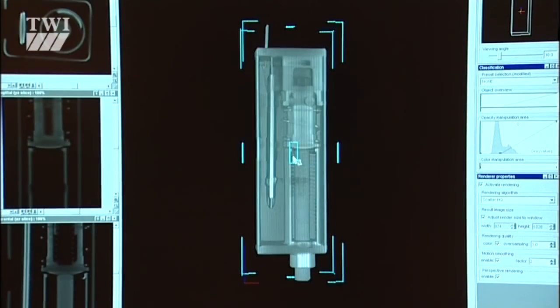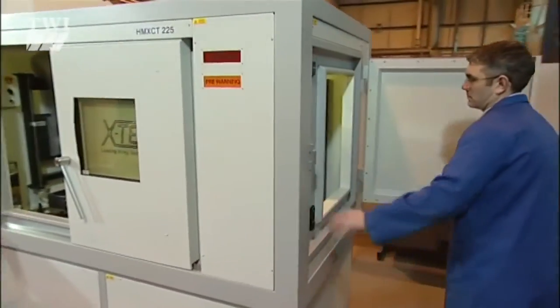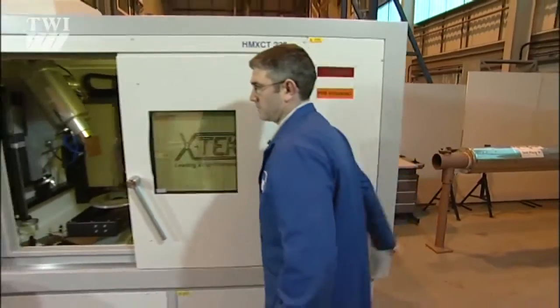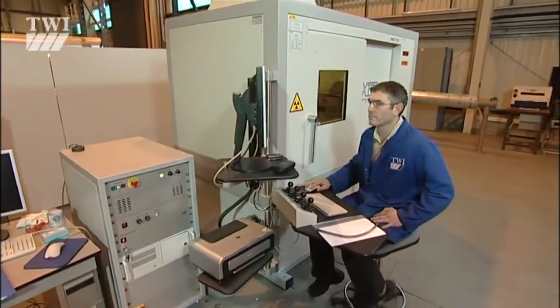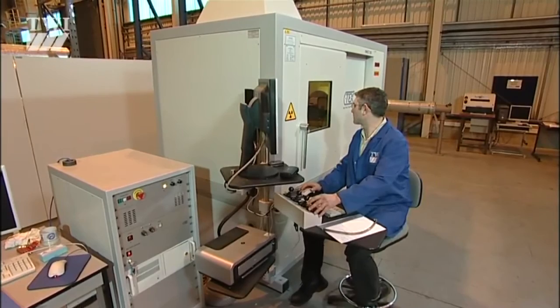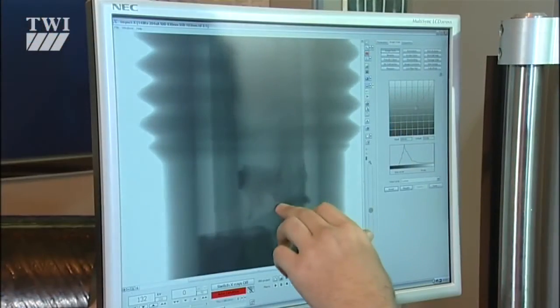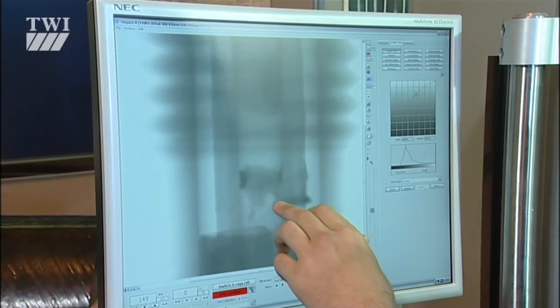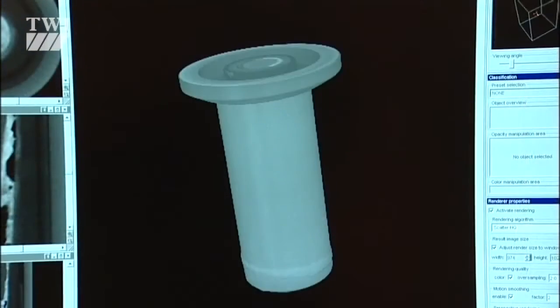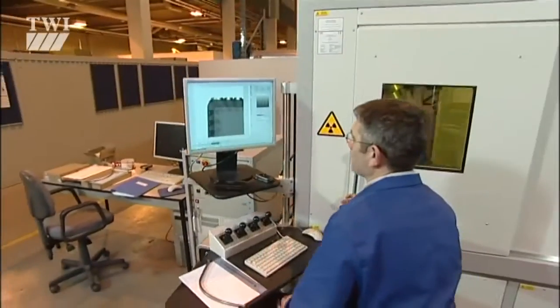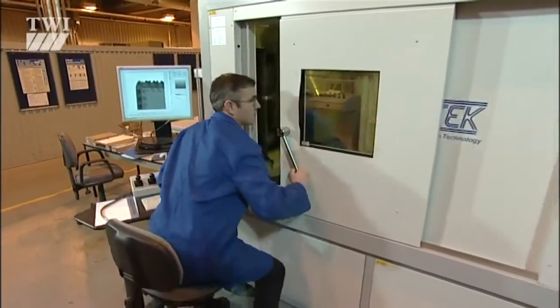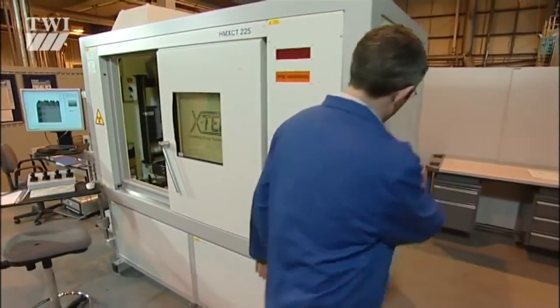Micro-focus test equipment differs from standard radiography in that the focal spot size is extremely small, typically in the micron range. The benefit is that it produces radiographs with extremely high definition, lending itself well to producing large magnification images while retaining good definition of tiny defects. Some benefits of digital radiography over wet radiography are obvious: there's no need for chemical processing, the exposure-to-image viewing time is shorter, the images are easily stored on a hard drive, and they can be easily manipulated and enhanced on a computer.